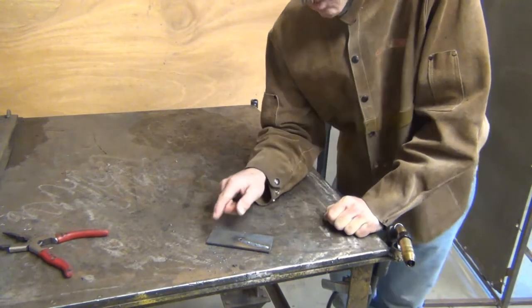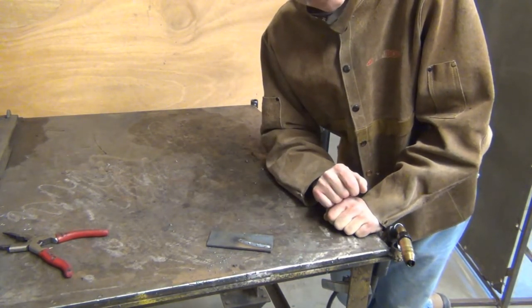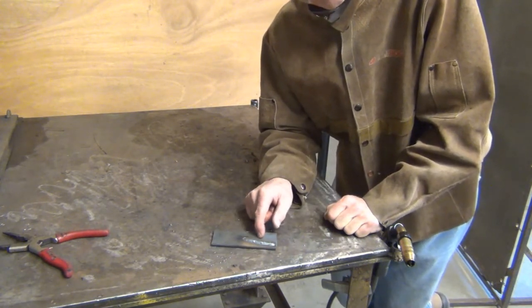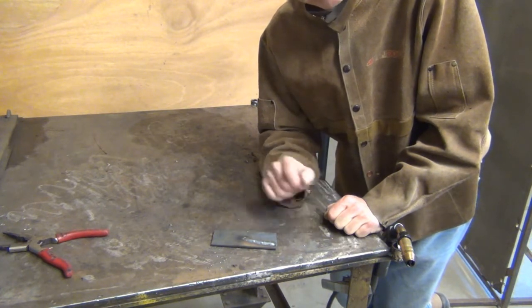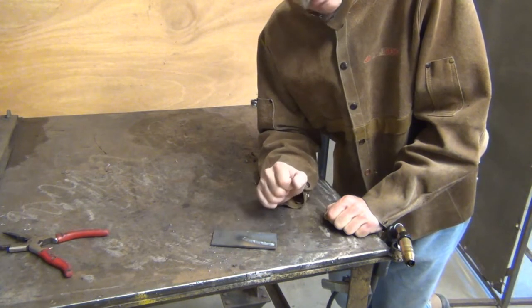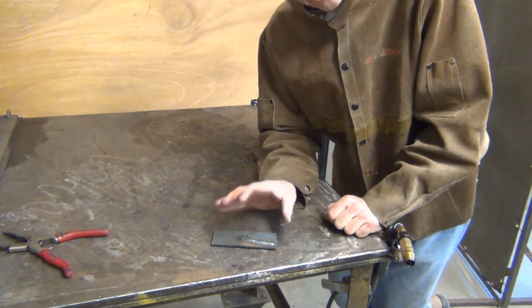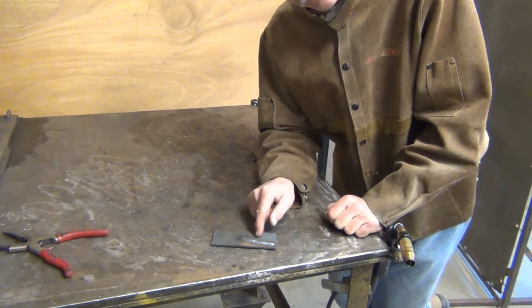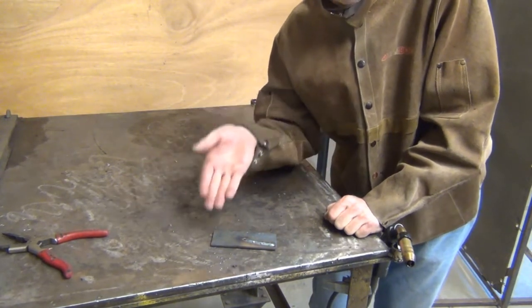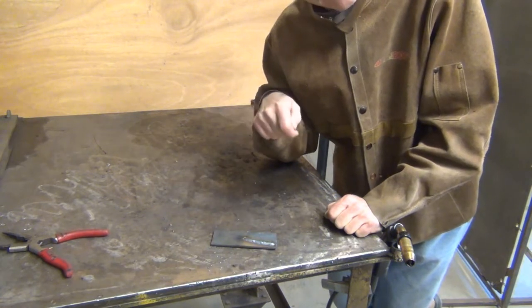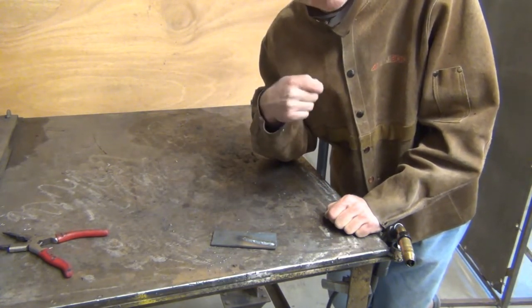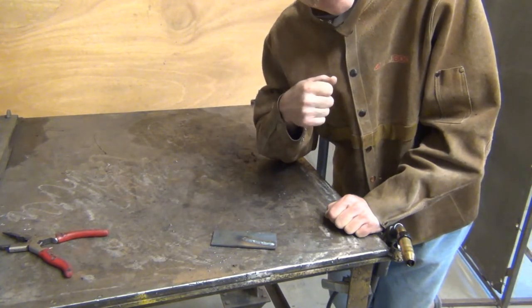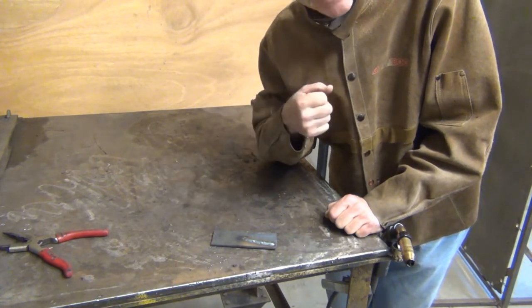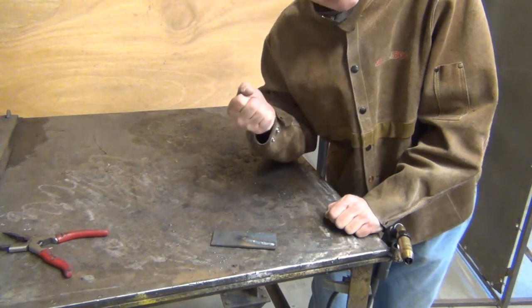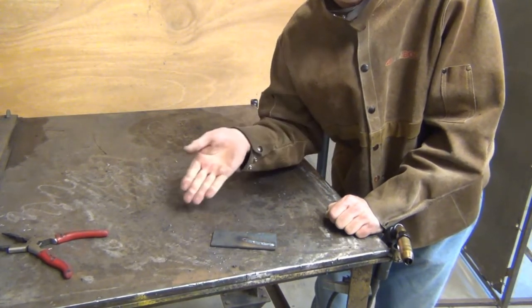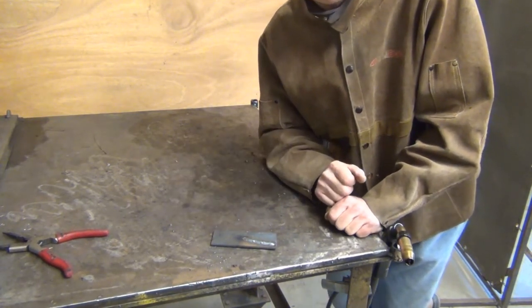Now, most of the material that will weld is hot rolled steel. So whenever we form steel hot, it develops an oxide. Okay? If we want our weld to be as strong as the host, we need to grind that off. We don't have to grind the whole thing off, just where we're going to do our weld. Because the mill scale will not vaporize. It simply falls into the weld like, I don't know, the crumbs at the bottom of the chip bag. So when it solidifies, it's not the same composition or solid throughout. Okay, so again, that's where your weld would fail.